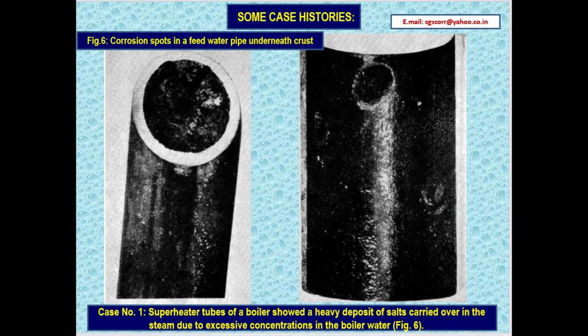Some case histories. Figure: corrosion spots in the feed water pipe underneath crust. Case study 1. Superheated tubes of a boiler showed a very heavy deposit of salts carried over in the steam due to excessive concentrations in the boiler water. You can see beneath the scales pits, crevices, holes.